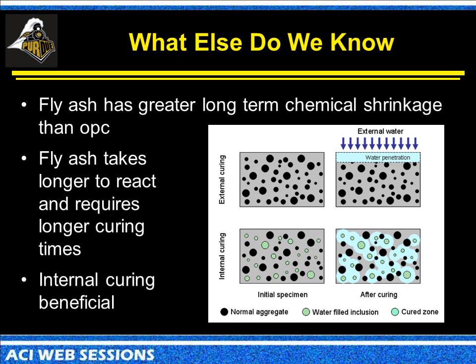Now, to get into the heart of what we're really trying to promote with bringing internal curing in with the concept of using higher volume fly ashes, we know that fly ash has a greater long-term chemical shrinkage. So when water and cement get together and react, they're going to undergo a volume change. 1 volume of water, 1 volume of cement get together and form about 0.84 volumes of overall reacted product. If you replace some of that cement with fly ash, you're going to double the amount of chemical shrinkage that's taking place in the system.